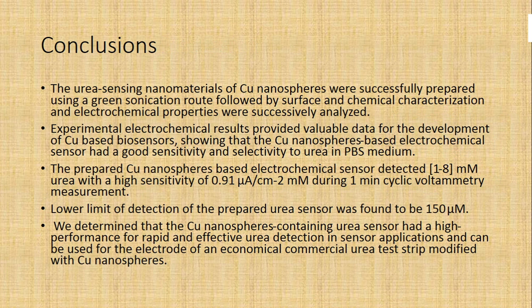Now, conclusions. As a conclusion, the following points were drawn. The copper nanospheres were successfully obtained and their electrochemical properties were successfully analyzed. Electrochemical sensors coated with copper nanospheres had a good sensitivity and selectivity towards urea in PBS medium. During a cyclic voltammetric scan of 1 minute, 1 to 8 millimolar urea could be detected with a high sensitivity of 0.91 microampere over centimeter squared per millimolar. The lower limit was found to be 150 micromolar.